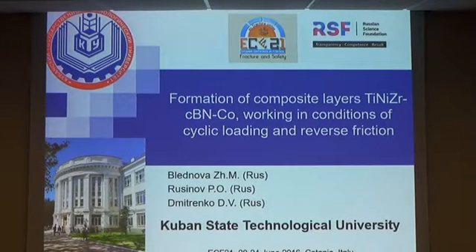We presented our work from Krasnodar, Russia, on the formation of a composite layer of titanium nickel zirconium with cubic boron nitride and cobalt, working in conditions of cyclic loading and reverse friction.